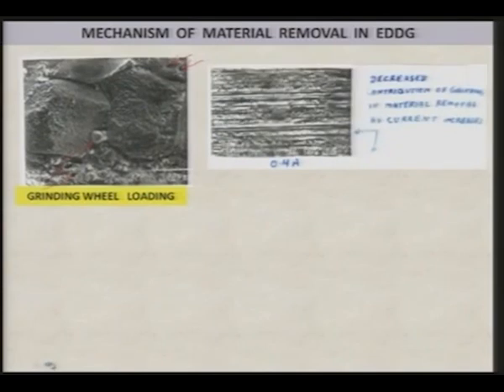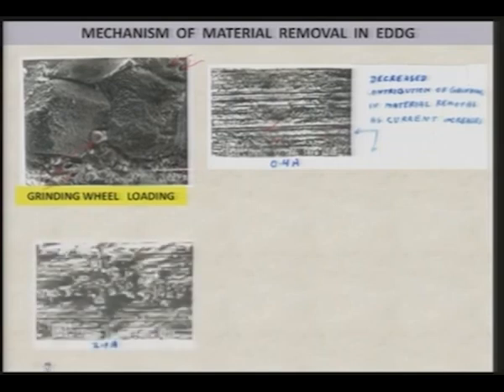Now, you can see here at 0.4 ampere current, which is quite low, grinding marks are quite visible, but there is a decreased contribution of grinding in material removal as current increases. I have shown it to you, I will show you again. These are the grinding marks, quite visible, but at some places you can see the craters also, which indicate that sparking is also contributing to the material removal.